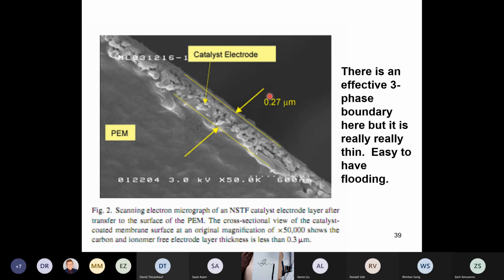And then what you do is you take that whisker-coated polyimide and you heat laminate it to the Nafion polymer electrolyte membrane. Okay, so here's the polymer electrolyte membrane, and here's the whiskers that have been heat laminated to the polymer electrolyte membrane. So we set up to do that here, and it's really trivial. You have a machine that you would use to make a student card, where you just have a photo on a piece of paper and you just run it through a laminator with plastic on each side and you get a hard student card. It was really that simple.